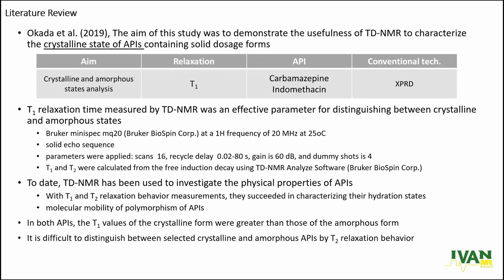In another study, they used TD-NMR to characterize the crystalline state of APIs in solid dosage forms. They measured the T1 relaxation times. Up to date, we know that TD-NMR has been used to investigate physical properties of APIs. With T1 and T2 relaxation behavior measurements, they succeeded in characterizing hydration state and molecular mobility. In both selected APIs, the T1 values of the crystalline form were greater than those of the amorphous form, but they said that it is difficult to distinguish crystalline and amorphous API by T2 relaxation behavior.